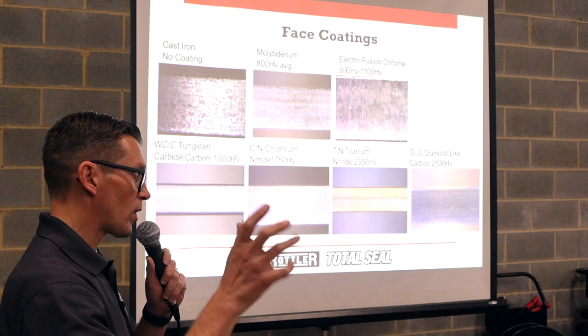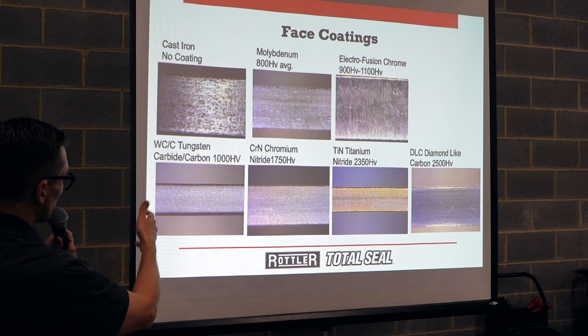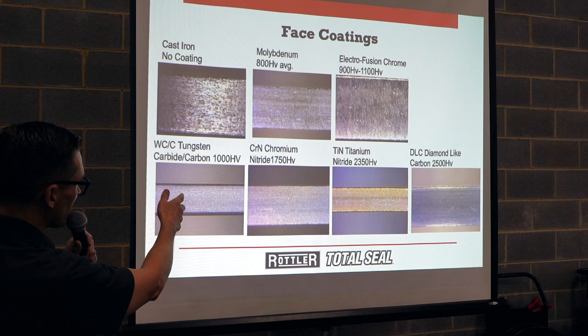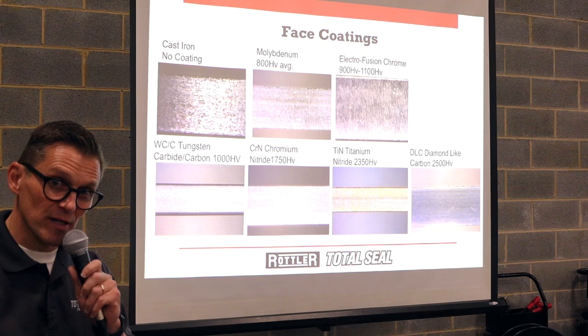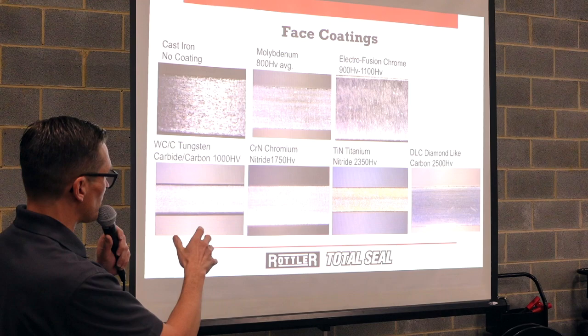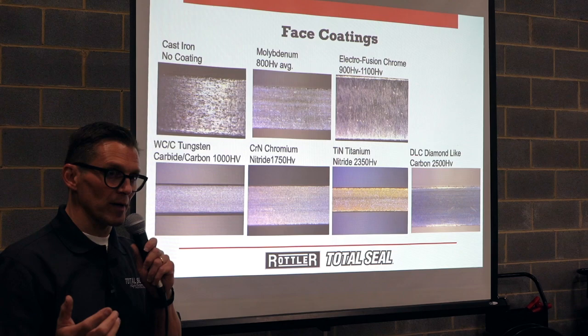When you get away from those, you get down to WCC, which is tungsten carbide carbon, a little bit harder than moly. Then you've got CrN, chrome nitride, the same stuff that's on titanium valves that makes them chrome looking. It's a PVD type of coating that's similar to chrome. It's hard, it's really good, about 1700 Vickers hardness. Then you've got titanium nitride, the gold coating. If you've got a gold-coated drill bit or insert that's your favorite one that lasts forever and cuts great, the reason is titanium nitride. That's what gives it that gold color.